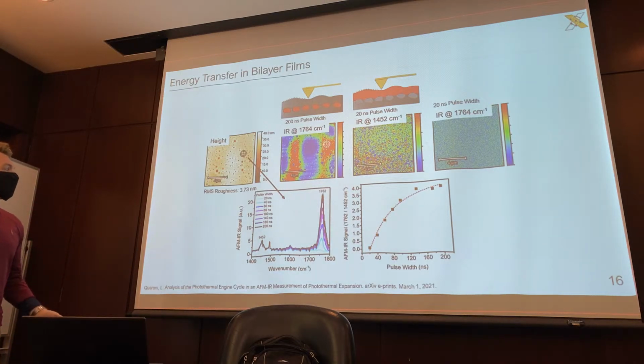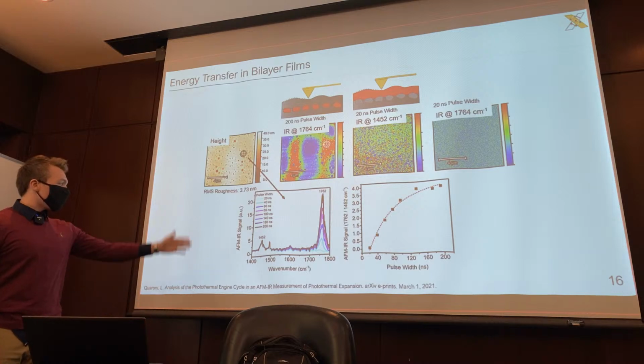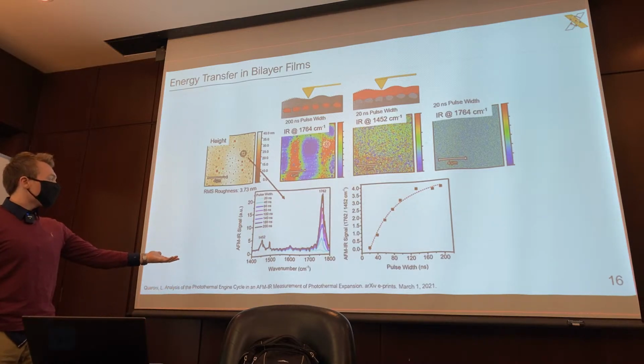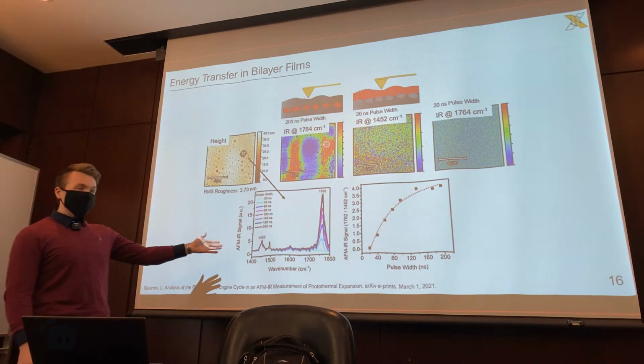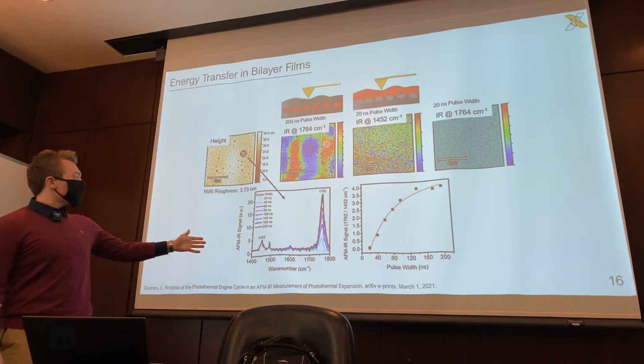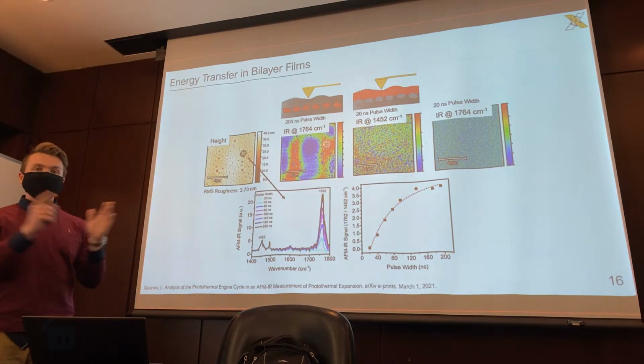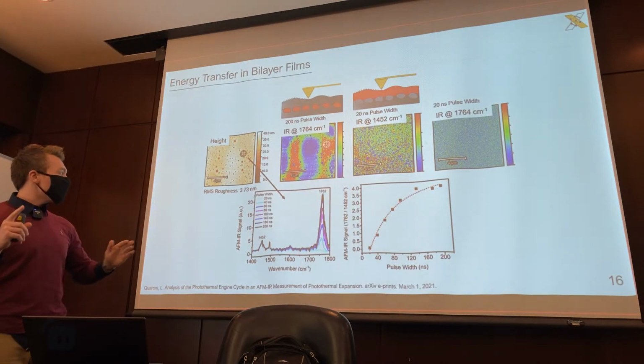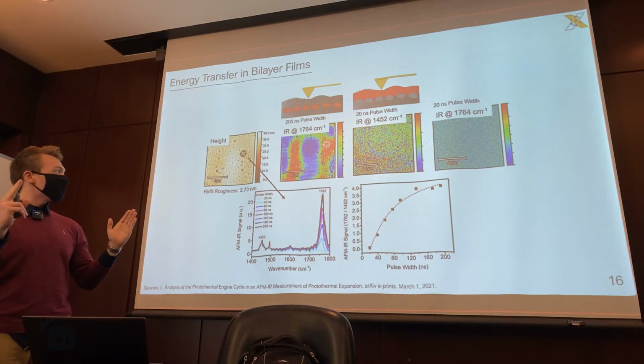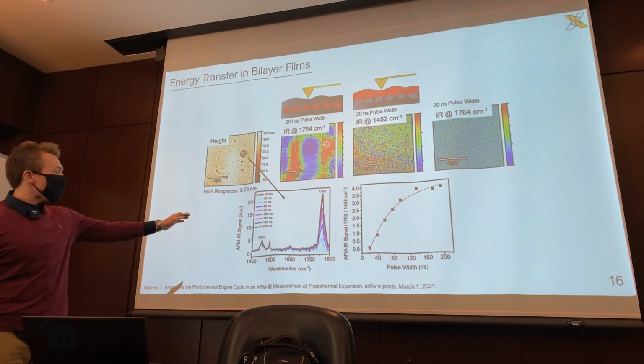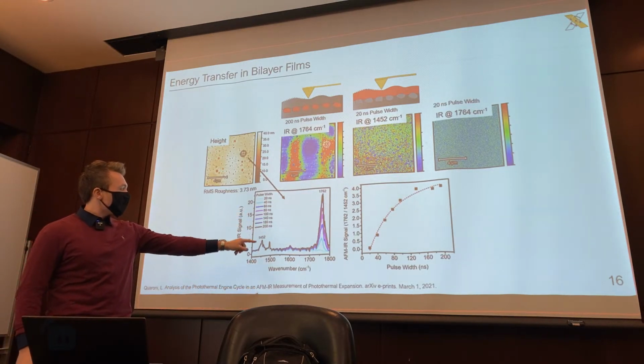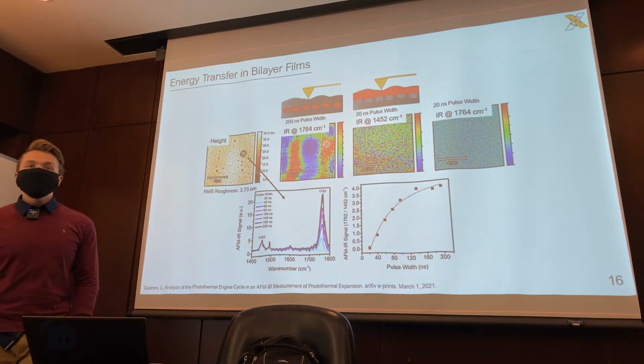So this can also be observed in these AFMIR spectra, where I took AFMIR spectra at various pulse widths. Now I normalized these to 1452, and so you can see when we maximize the pulse width, which is as far as our instrument can go, 200 nanoseconds long, and as we decrease that, we see a rapid disappearance of our PLA signal.